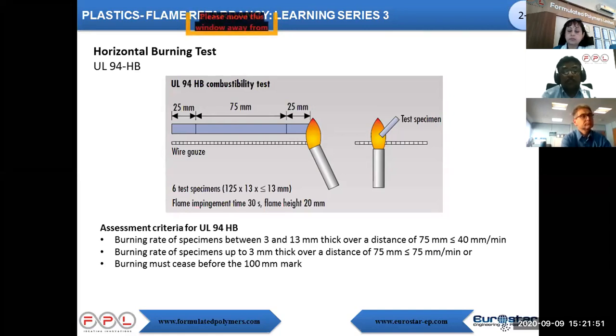Then the acceptance criteria for this test: the standard requires a burning rate of 40 mm per minute for a thickness of 3 mm and more. For less than 3 mm, we require 75 mm per minute. Then the fire should switch off before the 100 mm mark. And the other HB tests like HBF and HB1 have similar procedures and test conditions. Only the specimen changes, for foam-like materials.